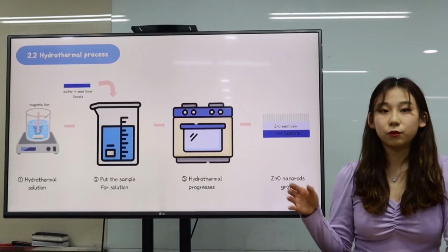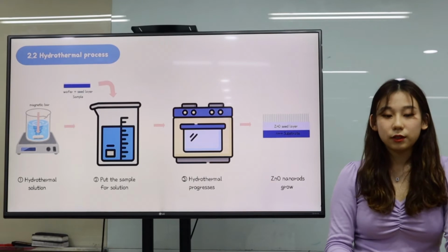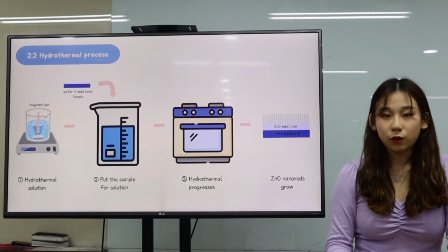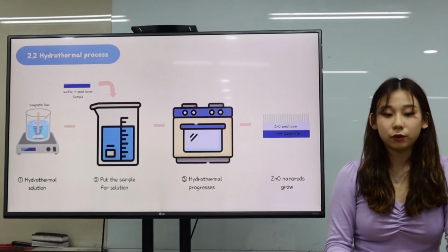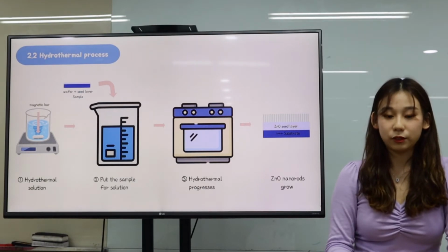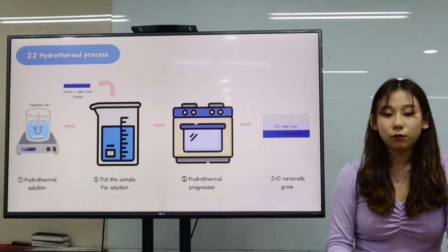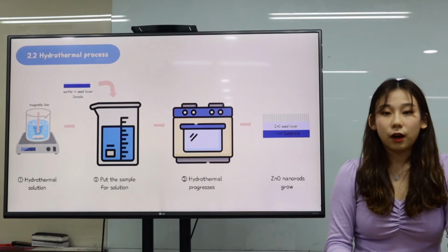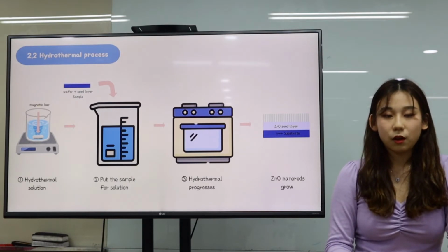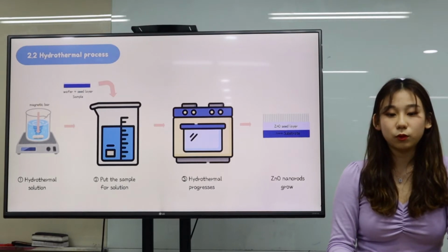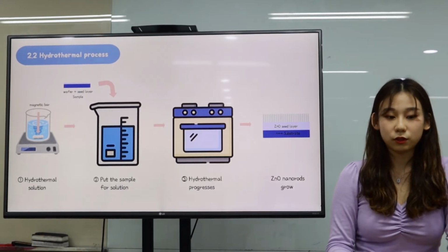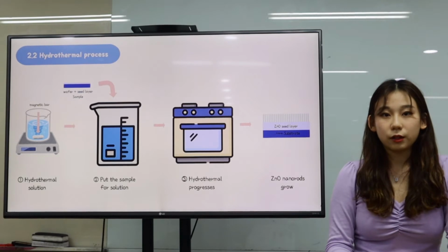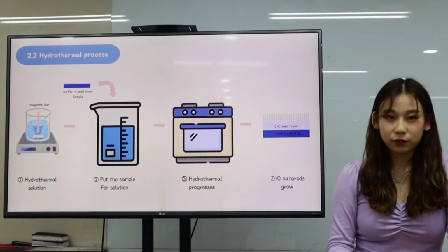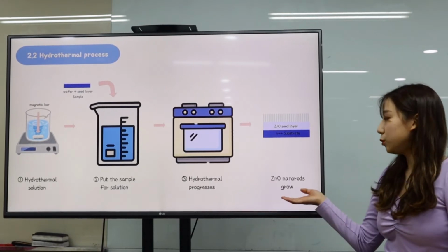Number 2, the hydrothermal process. First, to make the hydrothermal solution, we mix zinc nitrate powder and hexamethylenetetramine with a 1:4 ratio. Second, stir with the magnetic bar on the hot plate for 1 hour. Third, put the sample with the seed layer in the solution. Seal the beaker and put it in the oven for 6 to 12 hours. Then the nanorod will grow.